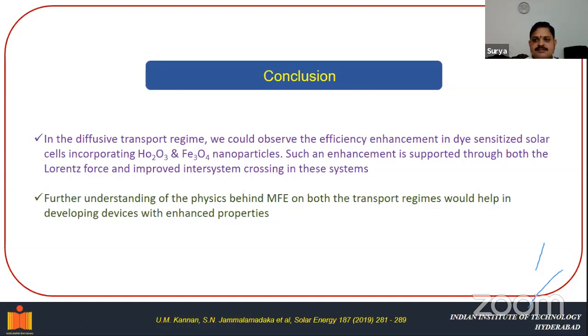So these demagnetization fields we tried to prove by different methods like magnetic force microscopy, phosphorescence experiments, and we have done the micromagnetic simulations, and then also the transverse matrix modeling. Such enhancement is supported through both the Lorentz force and improved intersystem crossing in the device as far as the holmium oxide is concerned. Whereas for iron oxide, it is due to the demagnetization fields, which lead to the Lorentz force effect that will enhance the efficiency of the solar cells. The further understanding of the physics behind the magnetic field effect on both transport regimes we have done using the transverse matrix modeling.